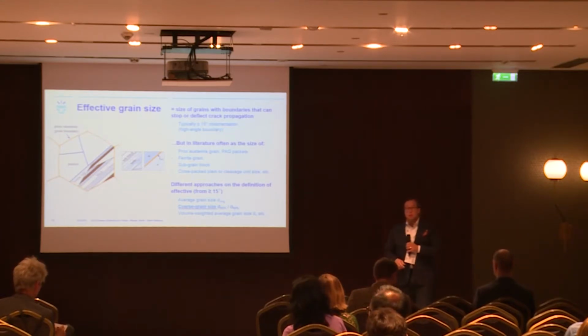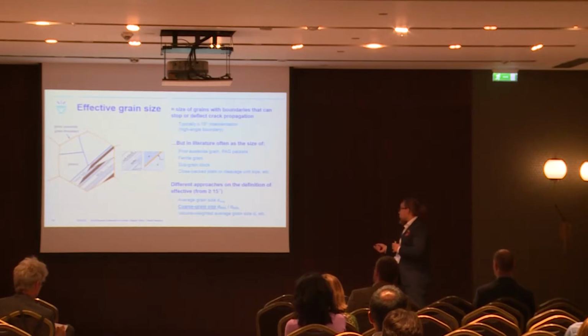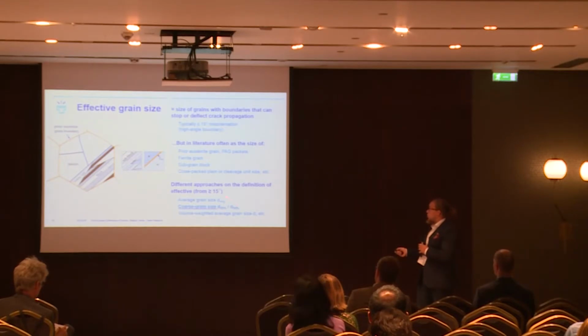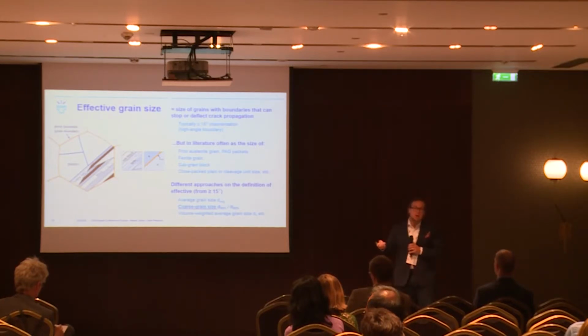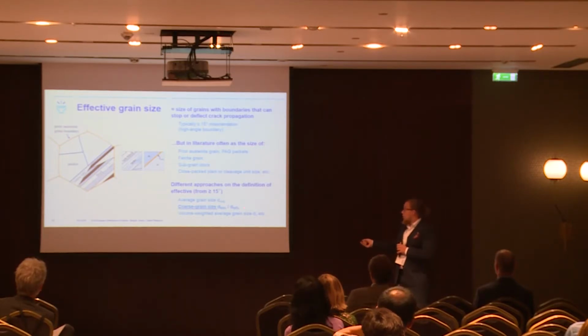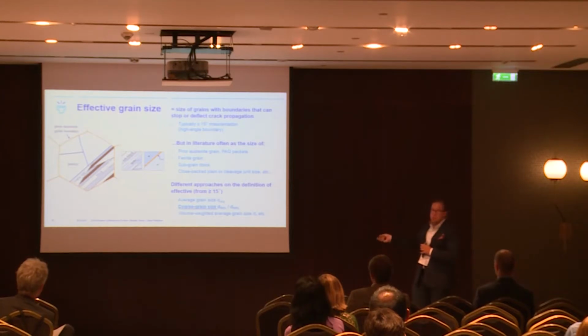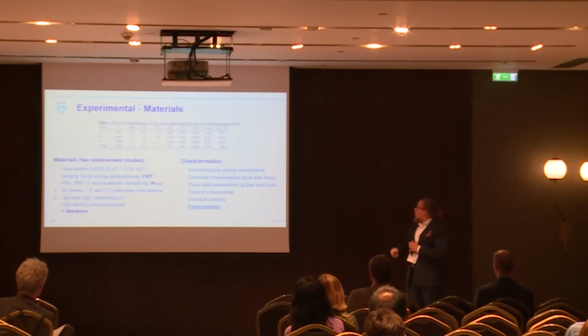And also in real-life microstructures we have a distribution of grains. The most used measure is the average grain size, but some recent advances have shown that it is the coarse grain size in the cumulative distribution that plays the key role. Of course, these use something like the 80% or 90% level of the distribution. That has also been done with different parameters for decades. But then to go to the experimental part.